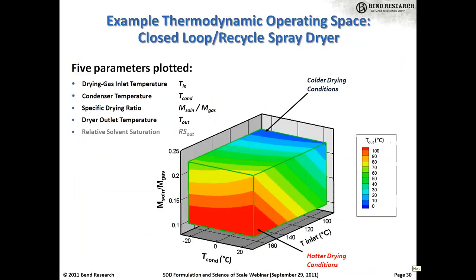So coming back to the graphical representation of the thermodynamic model, in this case we're adding another dimension to account for another parameter, the condenser temperature, which we need to account for the larger scale spray dryers, which operate in closed loop mode. So the drying gas is actually recycled as it comes out of the chamber. It gets passed through a condenser and then recycled back into the spray dryer. So because of that, it does contain some amount of solvent vapor that obviously affects the drying rate, and that affects the particle morphology. So we need to account for that condenser temperature.